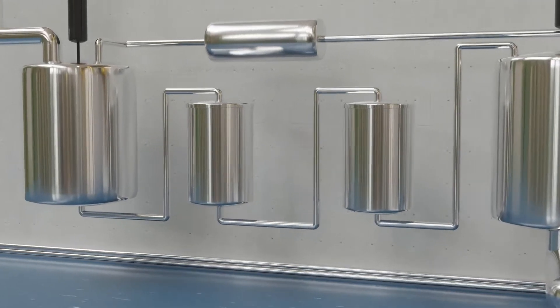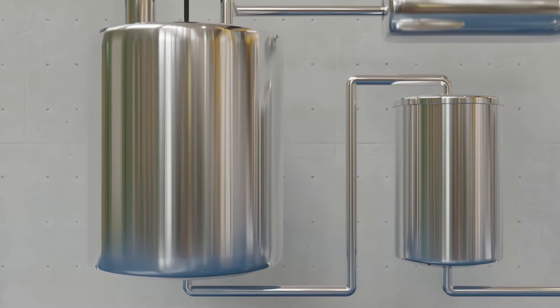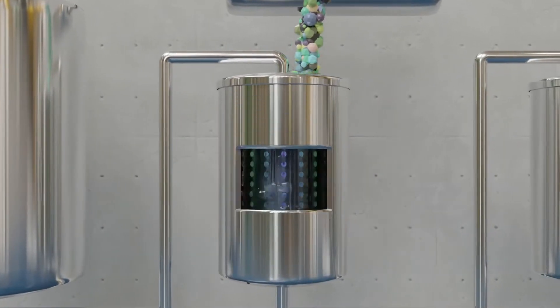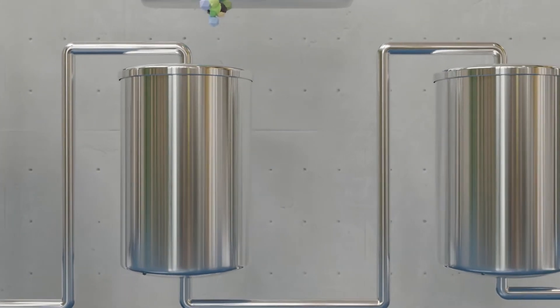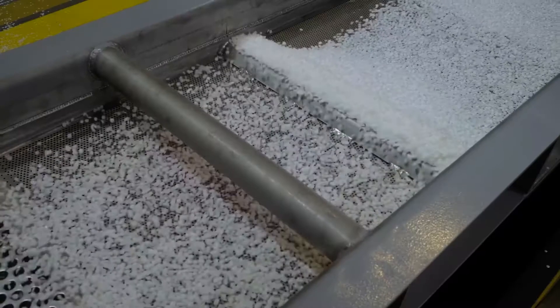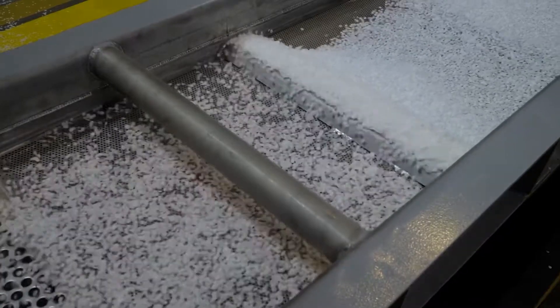This consists of one or more dissolution steps, depending on the number of target polymers for recovery, with the recovery order determined by the thermal and solubility properties of the polymers. The MultiCycle approach has been demonstrated for a range of commercially relevant plastics, variously incorporating polyethylene, polypropylene, polyamide and PET.